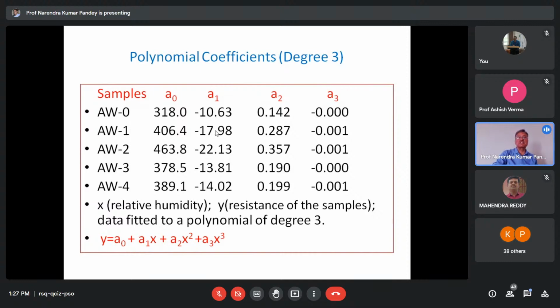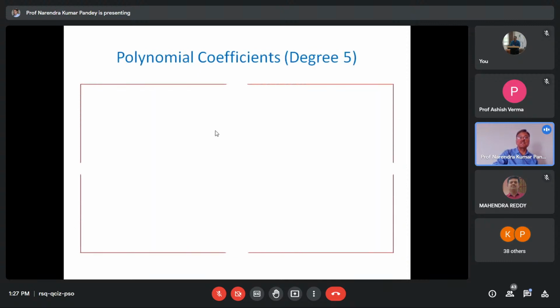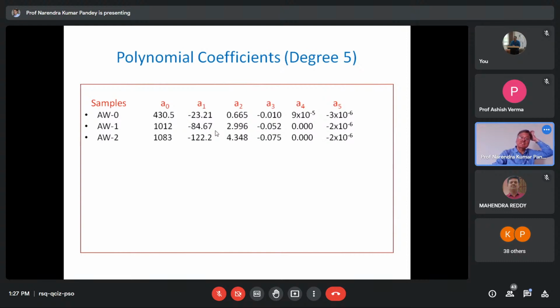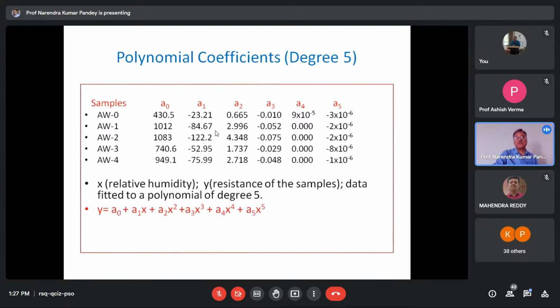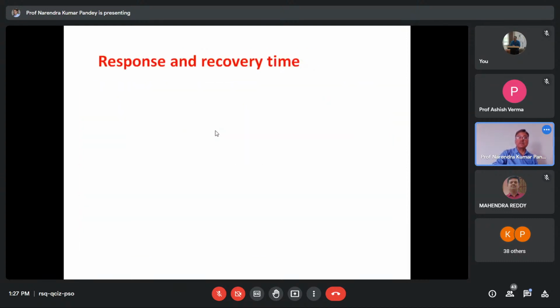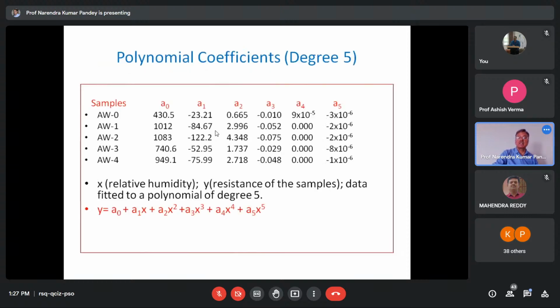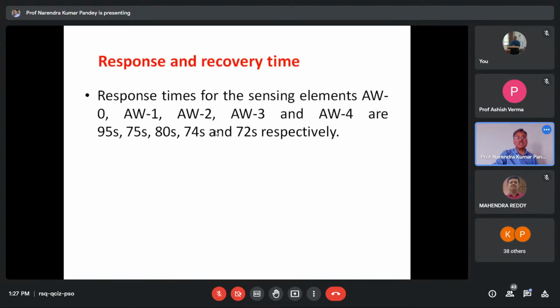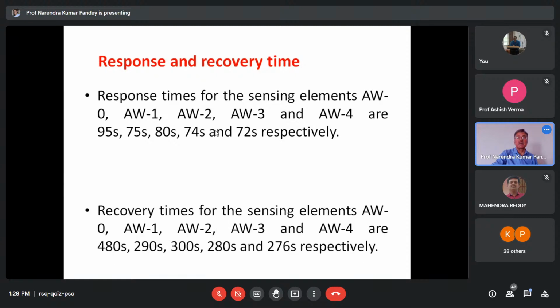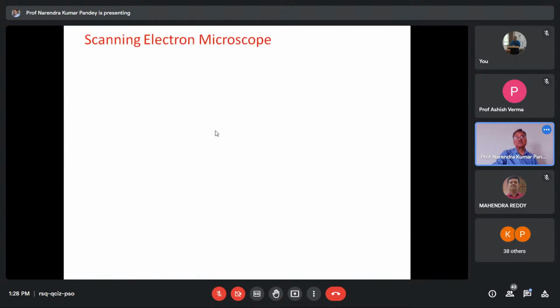Relative humidity versus resistance. Then polynomial coefficients of degree 5 were established for some samples, and these are the coefficients. Relative humidity versus resistance. Response recovery times for AW-0, AW-1, AW-2, AW-3, AW-4 were 95, 75, 80, 74, 72. So the response times were decreasing with increase in the loading percent. Recovery times were also decreasing.